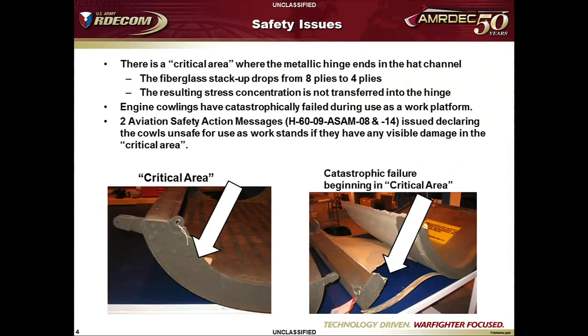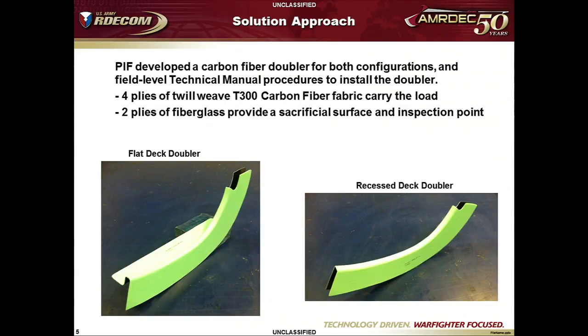There are currently 2 ASAMs out there on the engine cowling. It cannot be used as a maintenance platform in its current condition right now. What we did is we developed a doubler that would go over top of that hat section on the edges of the engine cowling where that critical area is. The doublers are made out of 4 plies of T300 carbon fiber with the plies orientated in the direction of the load, of the stress. At the top of that hat section, it's 4 plies on each side, and at the top of that hat section, they overlap. So you end up with 8 plies of T300 carbon fiber, so it becomes extremely, extremely robust.